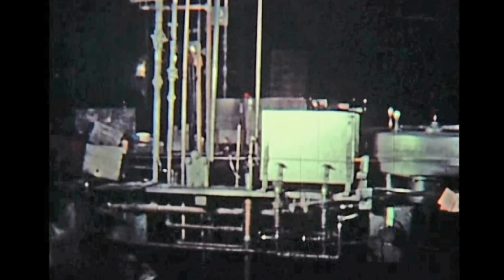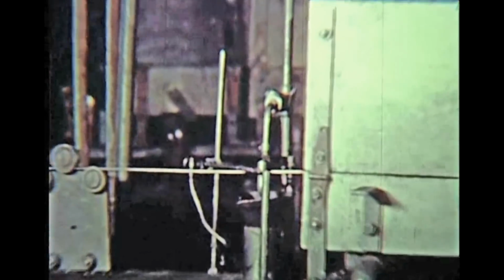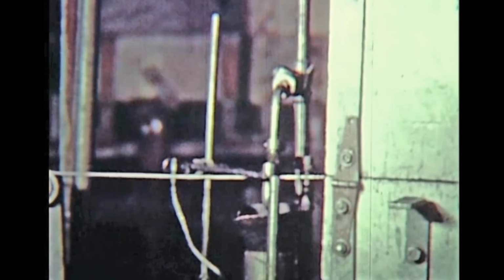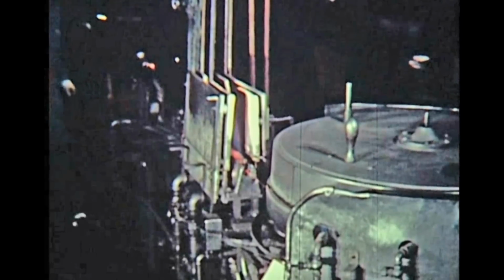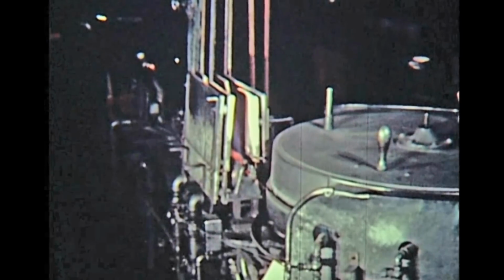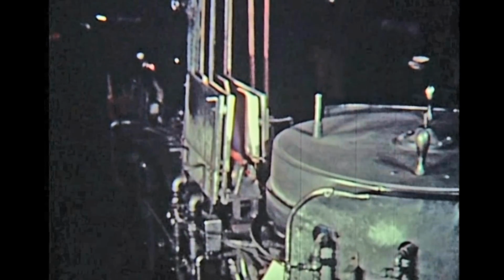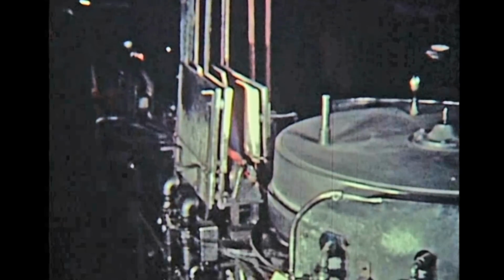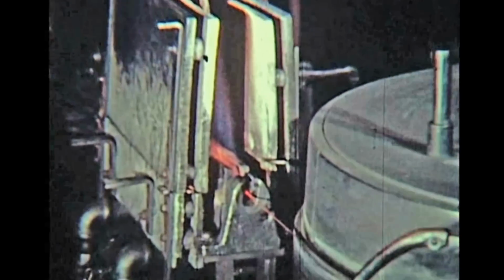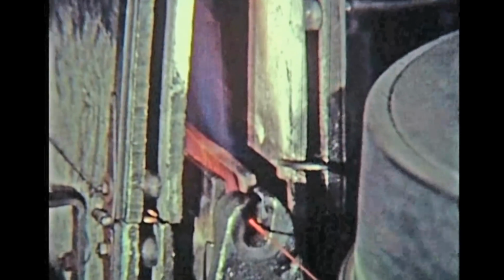Drawing is the process of pulling the heated rod through a die slightly smaller than the rod. First, it passes through a graphite lubricant, which reduces die wear and also protects the wire from excessive oxidation. It then continues through a burner, which bakes on the lubricant and brings the wire to the proper temperature so it can be pulled through a die, which reduces the wire diameter and increases its length. By special lighting, we can see this dramatic reduction in size.